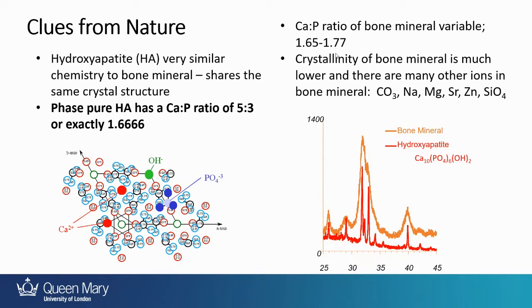So this is where hydroxyapatite comes in. Hydroxyapatite has a very similar chemistry to natural bone mineral. So it's got the same crystal structure. But the difference between phase pure hydroxyapatite and bone mineral is that phase pure hydroxyapatite, this is its crystal structure here, basically has phosphate ions in it, OH, so hydroxyl ions, and calcium, and nothing else. And phase pure hydroxyapatite has a calcium to phosphorus ratio of 5:3. That's just basic calculation of maths from how many calciums there are to phosphates in the unit cell.